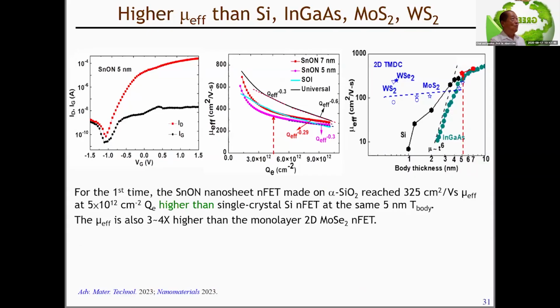So how about the mobility? For the first time, the SnON nanosheet NFET made on amorphous silicon dioxide reaches a high mobility of 325 cm²/V·s at 5E12. The red point here is even higher than single crystal NFET at the same 5 nanometer body thickness. Please notice that our data is also 3 to 4 times higher than the 2D materials.